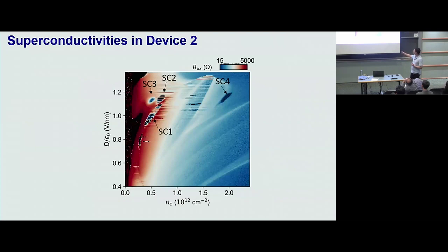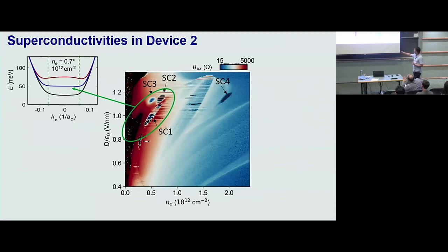I call them SC1, SC2, SC3, and SC4. Phenomenologically, you probably already noticed that they look very different, in the sense that the regions of SC3 and SC4 seem to be uniform, while the regions of SC1 and SC2 are very fluctuating. Not only are SC1 and SC2 fluctuating, but this big region next to it is also fluctuating. Okay? And as I said, this region corresponds to when you open up the band gap by using a big displacement field, and you squeeze the bottom of the conduction band to make it really flat, and you put charges in there, and you get these 4 states.